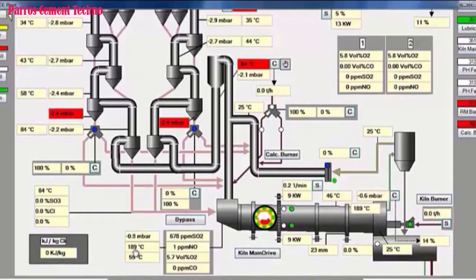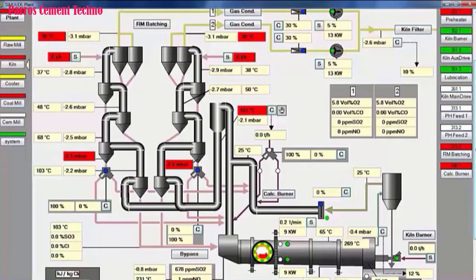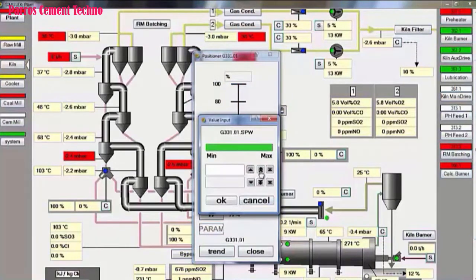Heating up has been running for about 2 hours, and the temperature in the sintering zone is almost the same as that in the kiln inlet. The temperature in the sintering zone should be higher, because at the first start, the air inlet to the preheater system was too fast, so that a lot of temperature was pulled into the kiln inlet. Now the temperature in the sintering zone has started to rise faster compared to the temperature in the kiln inlet. Before we add more fuel consumption, we first increase the opening of the preheater ID fan damper from 30% to 40% for line 1 and line 2.